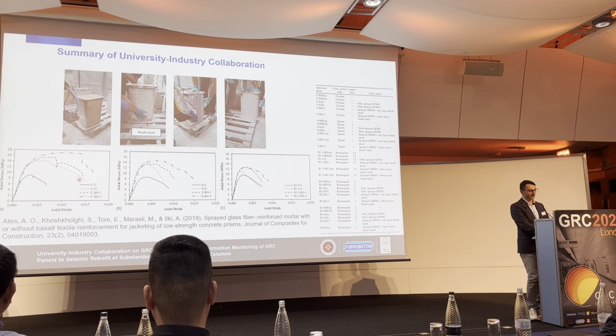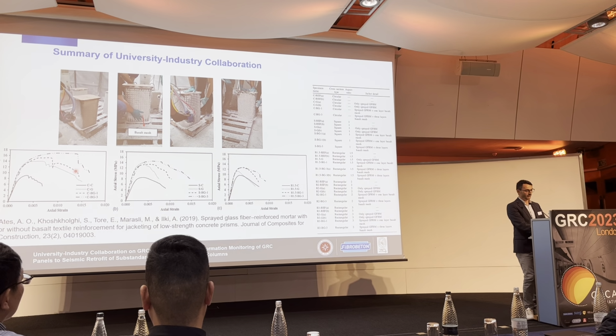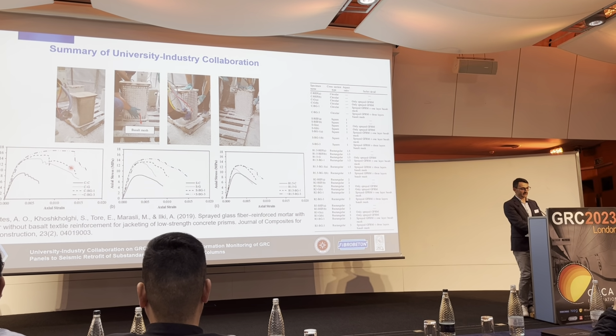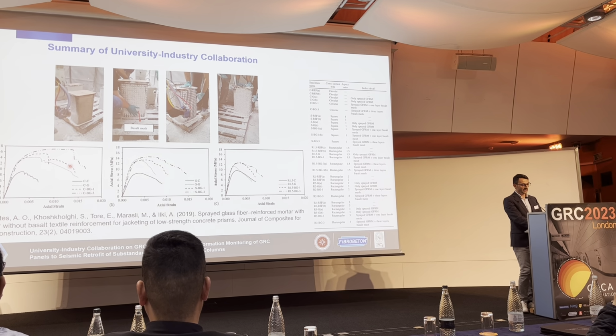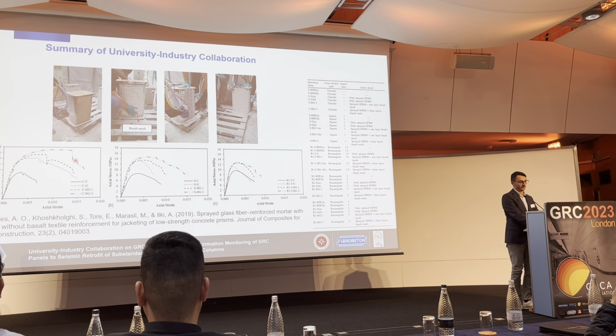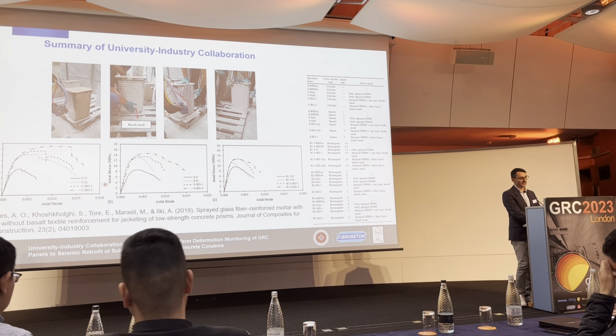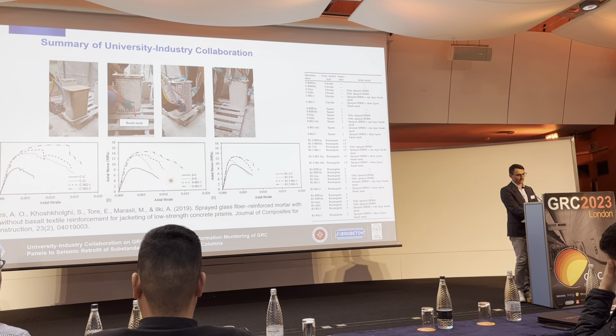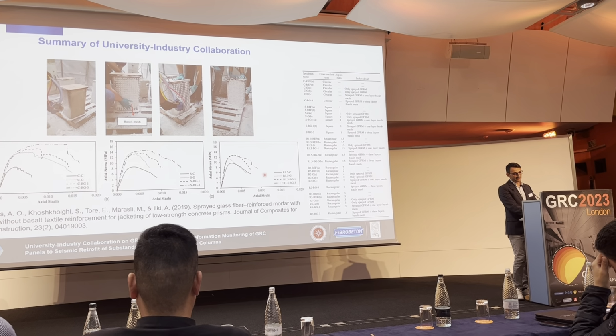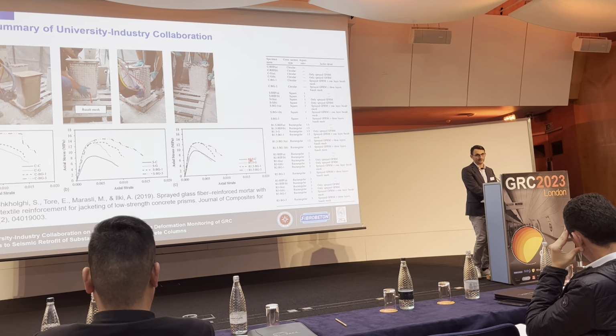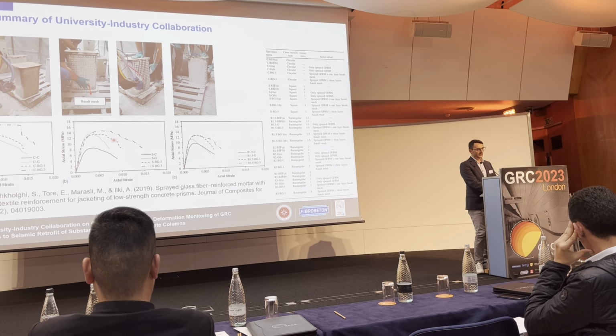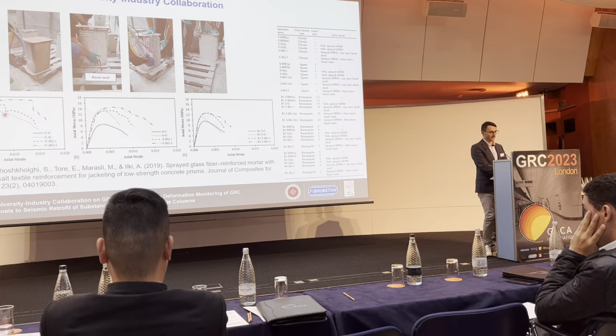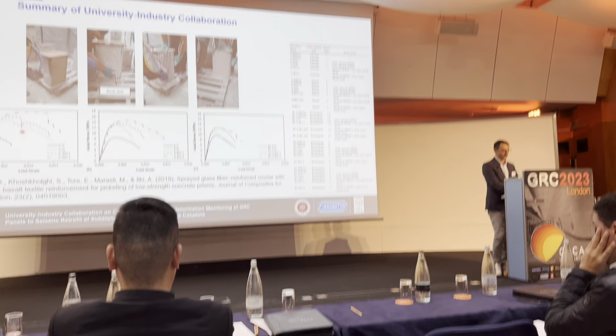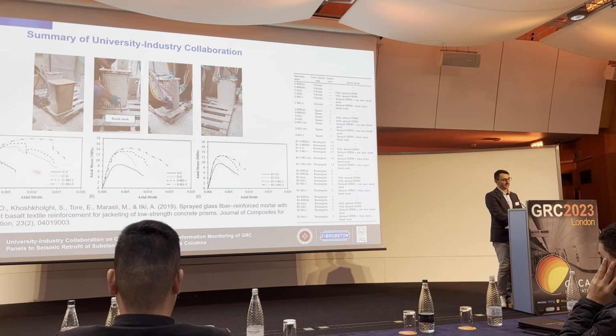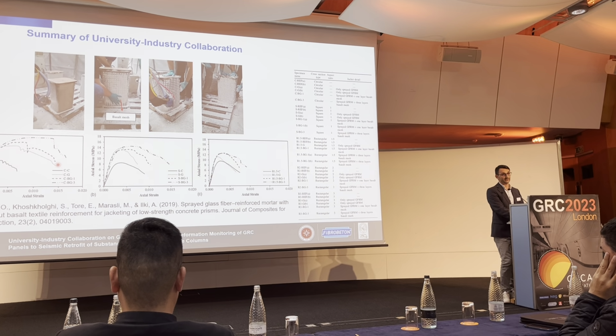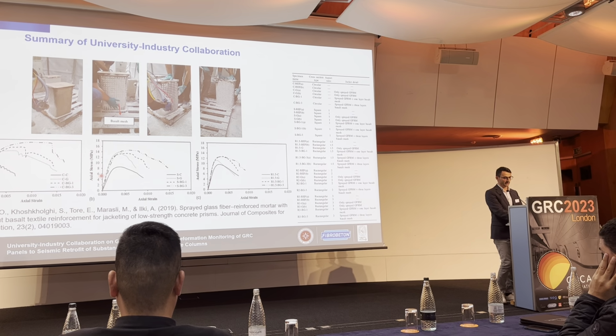And this is plain GRC. Over it, you see the GRC combined with 1 layer of basalt mesh, and the upper one is the GRC with 3 layers of basalt mesh for the circular cross section. In the middle, you see the results for the square cross section in the same manner. And on the right-hand side, you see the rectangular ones with a cross sectional aspect ratio of 1.5. As expected, due to the confining pressure provided by the jacket, we have a significant enhancement in axial behavior. So it's very critical for us.